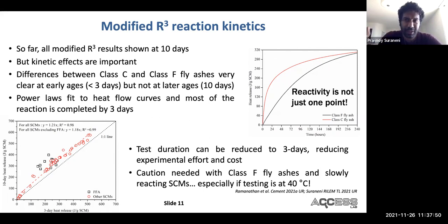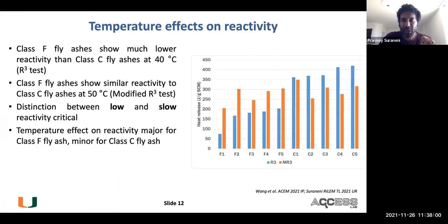Now, I mentioned before that the R3 test is done at 40 degrees. As you can imagine, you may want to be even more careful at 40 degrees. What I mean by that is this. This is a figure which is showing both R3 and modified R3 results for 5 class F fly ashes and 5 class C fly ashes. I've arranged them in increasing order of heat release from the R3 test. So what you see here is that if you compare the class F and the class C fly ashes, at 40 degrees, which is the R3 test, the class F fly ashes have far lower heat release than the class C fly ashes. In many cases, it's about 40-50% lower.